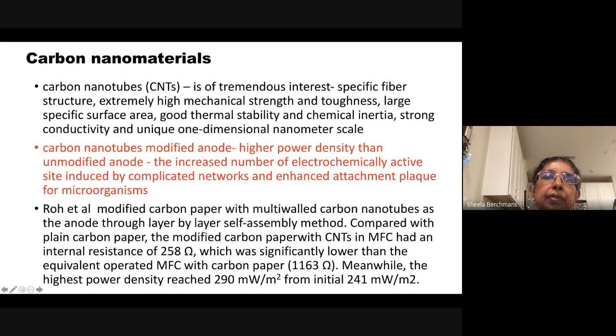Again, carbon nanotubes play a significant role in the development of microbial fuel cells. It is of tremendous interest, as I have told you, in the case of enzymatic fuel cells. Its special fiber structure, high mechanical strength, toughness, large surface area, good thermal stability, chemical inertia, strong conductivity, and unique one-dimensional nanometer scale material all contribute to the significance of carbon nanotubes in the development of microbial fuel cells. So a carbon nanotubes modified anode leads to higher power densities than the unmodified anode because it increased the number of electrochemically active sites induced by complicated networks and enhanced attachment of microbial film.